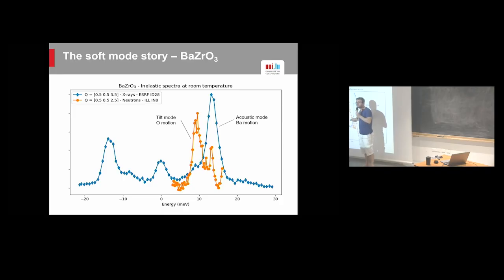This one is not as sharp, but this one doesn't have to do with the resolution. It has to do with the dispersion and the resolution in Q space. So this is another issue. I commented on which atoms contribute. I commented on scan. Of course, neutrons are expensive, so we don't measure everything in that case, right? We limit ourselves to a narrow energy range, where in X-ray they can take a bit more time.